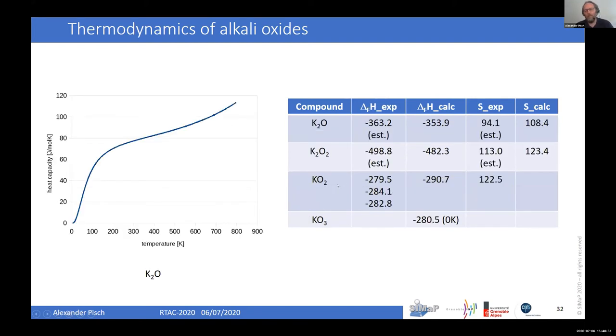And then comes the starting point of why we started this work on alkali oxides, which is to check the data on potassium oxide. And there you see that the estimated data in the literature, which is based on Janaf, is not so bad for the heat of formation. So we have an error of, let's say, 3 to 4%.